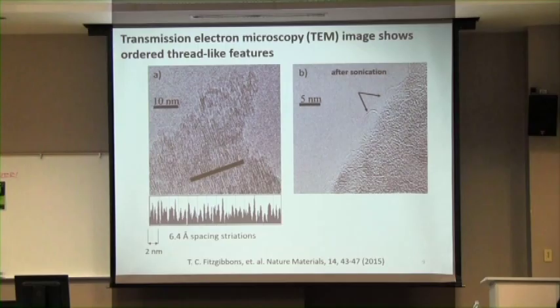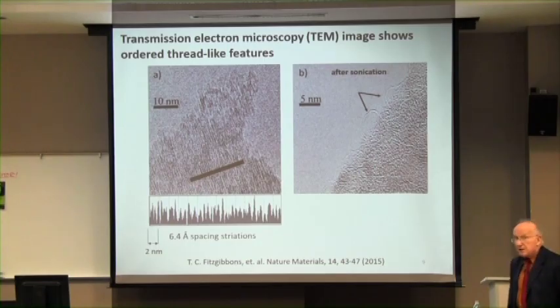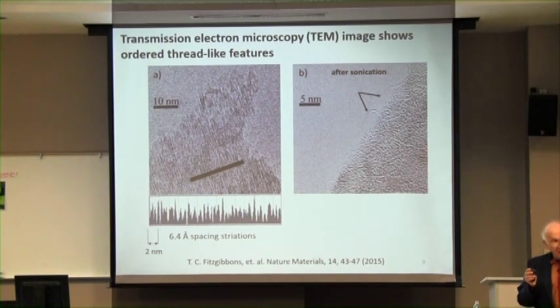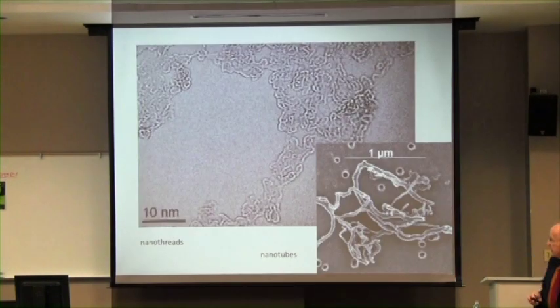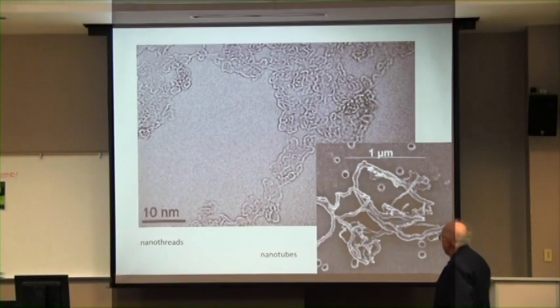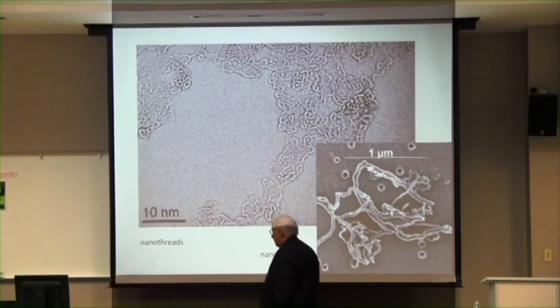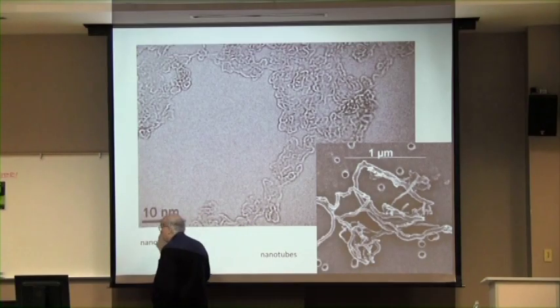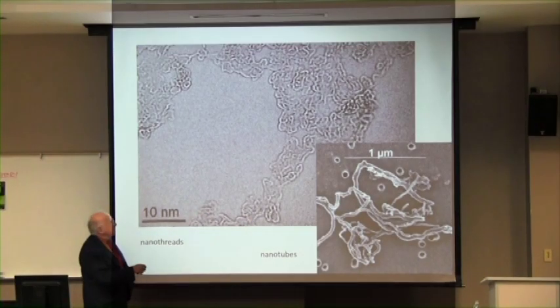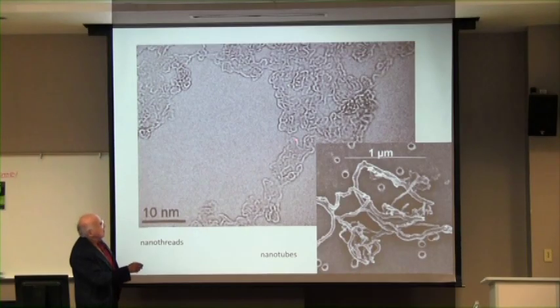But now the scale is what's really incredible, because that's 10 nanometers. 1 nanometer is 10 angstroms, so that's 100 angstroms. And this is a scan across that bar, and the striations are 6.4 angstroms. So these are now molecular scale. In contrast, you may know about nanotubes. There are beautiful pictures of nanotubes. But if you actually look at the material, it does look like a bunch of spaghetti, and so does this. These are the nanothreads.